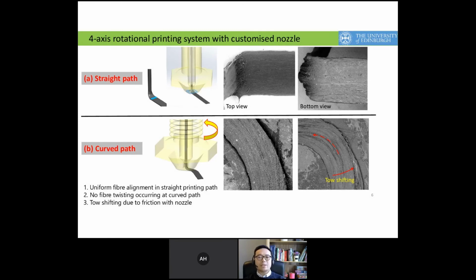We then tested both straight and curved single print passes. As you can see, as expected in the straight print pass, the fibers are almost perfectly aligned with the print direction. The shape of the printed strip is also quite consistent and accurate. In particular, when we print the curved pass with rotation, there is no obvious fiber twisting. The friction between the nozzle and the filament induces a tow shifting, which seems to mitigate the fiber breakage and fiber folding, but still maintains a good printed shape.